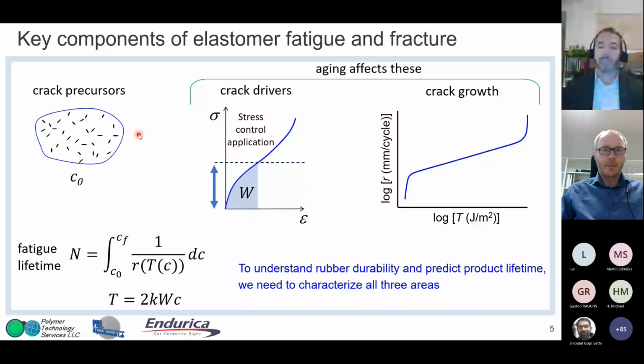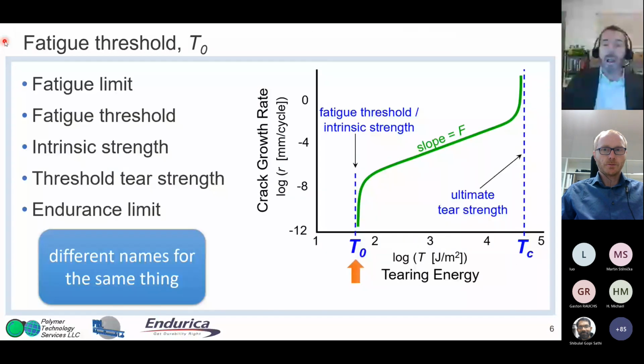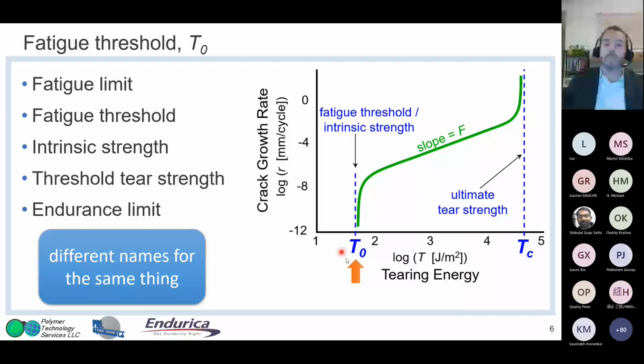So the talk today is about the fatigue threshold, which is this T0, T sub 0. And you can see that it's a lower limit of a fatigue crack growth. So if you plot log crack growth versus log tearing energy, there is some limit below which crack growth doesn't happen. And so this is a very important parameter because if you can operate somehow below this limit, then theoretically you could have an infinite fatigue lifetime, not including other things like aging or other changes to the material, of course. This has a lot of different names.